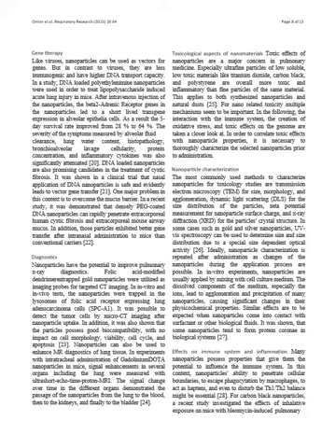In in vitro experiments, nanoparticles are usually applied by mixing with cell culture medium. The dissolved components of the medium, especially the ions, lead to agglomeration and precipitation of many nanoparticles, causing significant changes in their physicochemical properties. Similar effects are to be expected when nanoparticles come into contact with serum or other biological fluids. It was shown that some nanoparticles tend to form protein coronae in biological systems.